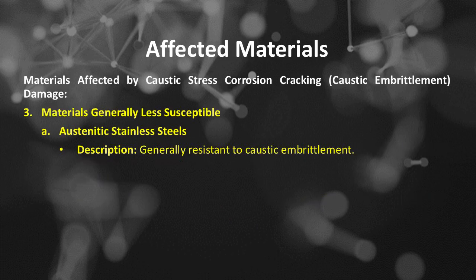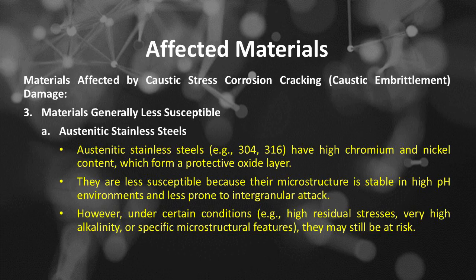Number 3 of materials affected by caustic stress corrosion cracking or caustic embrittlement damage is materials generally less susceptible, which includes: number A, austenitic stainless steels, generally resistant to caustic embrittlement. Details of austenitic stainless steels. Material affected by CSCC, austenitic stainless steels, such as 304 and 316, have high chromium and nickel content, which form a protective oxide layer. They are less susceptible because their microstructure is stable in high pH environments and less prone to intergranular attack. However, under certain conditions, such as high residual stresses, very high alkalinity, or specific microstructural features, they may still be at risk.